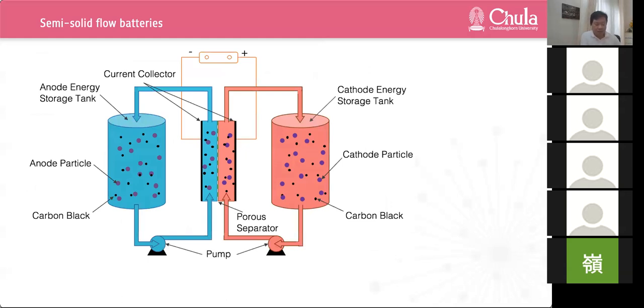Because redox chemistry is currently limited by the solubility of the electroactive species, the concept of a semi-solid flow battery has been proposed. In this system, the particulate active materials are dispersed in the electrolyte as suspension, essentially achieving infinite solubility compared to traditional redox solution. To achieve electronic charge transfer between the active material particles and the current collector, the active material and conductive additive were dispersed in a typical lithium-ion battery electrolyte solution to form a percolation nanoscale conductor network in the flowable electrode suspension. The high solubility of the active material in suspensions and the high cell potential lead to significant increases in energy density.